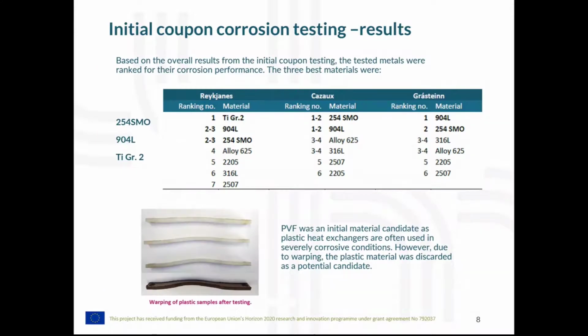And to recommend the material for a heat exchanger for Enogia's heat exchangers within the Rover C power plants, we compiled the relative performance of the various material candidates, and the results were that 254 SMO, 904L, the highly alloyed stainless steels, and then titanium grade 2 were the best performing materials, and thus most considered for